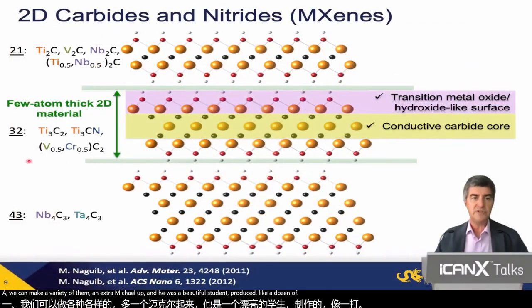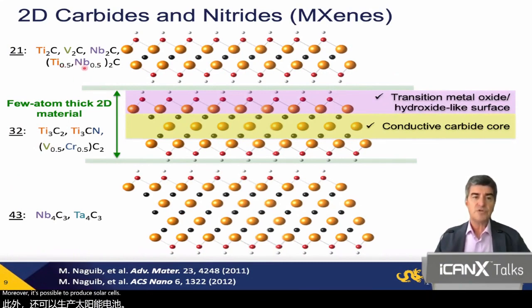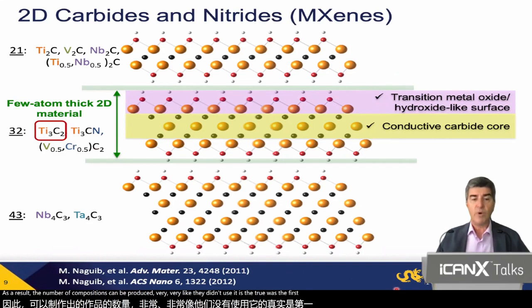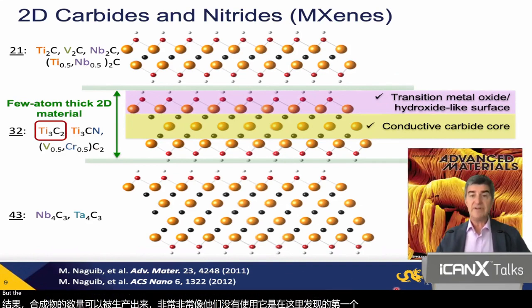Moreover, they come in several different groups with different numbers of layers in the structure. We can make a variety of them, and actually Michael, when he was a PhD student, produced about a dozen different compositions. Moreover, it's possible to produce solid solutions, mix different transition metals, or mix carbon and nitrogen. As a result, the number of compositions that can be produced is very, very large. Titanium carbide Ti3C2 was the first one discovered here, but discovery continues.